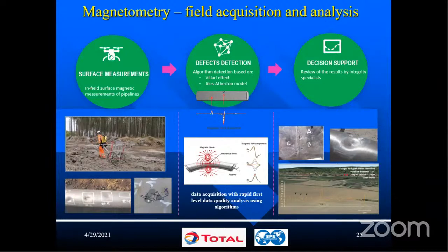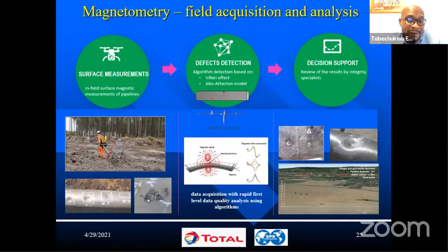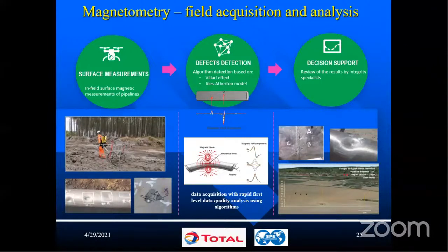Okay, so in this case, we can perform surface measurements of this residual flux of the pipeline using highly sensitive triaxial magnetometers. So as you can see, you can deploy this either on a wagon or driven over the top of the pipe. With this, we detect or register the residual flux.